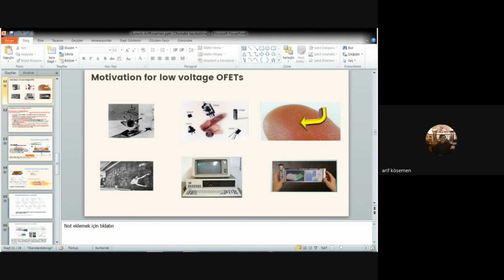Although there are several strategies for enhancing the low voltage operation capacity, high K dielectric materials, meaning high dielectric constant materials, ultra-thin dielectric materials, electrolyte-based dielectric materials, and interface engineering, lots of issues are still unsolved and need to be followed. For example, the use of a high-k dielectric layer usually leads to the problem of interface dipoles, and this damages the performance of the organic field effect transistors. If you use an ultra-thin dielectric layer, it is susceptible to rupture and breakdown when it deforms. It can deform very easily because it is very thin.